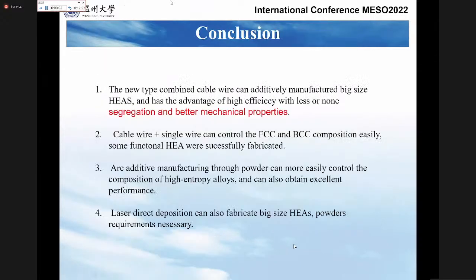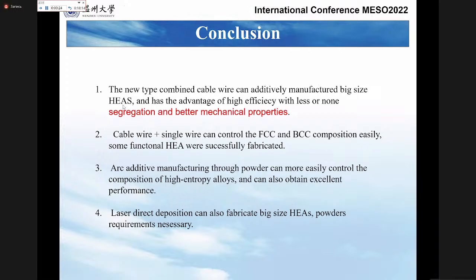Okay, the conclusion is: first, we use a new type of combined cable wire to additively manufacture big size HEAs, high entropy alloys, with the advantage of high efficiency, less or no segregation, and better mechanical properties. Second, cable wire plus a single wire, a dual wire, can control the FCC and BCC composition easily, and precipitation. Some functional HEAs were also successfully fabricated.